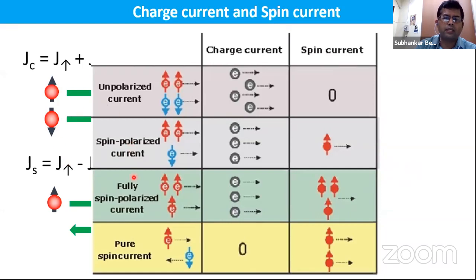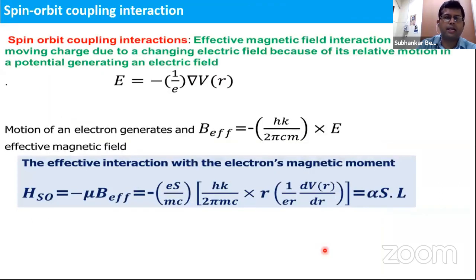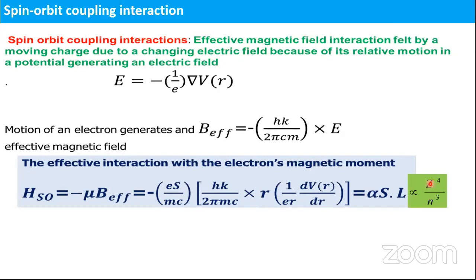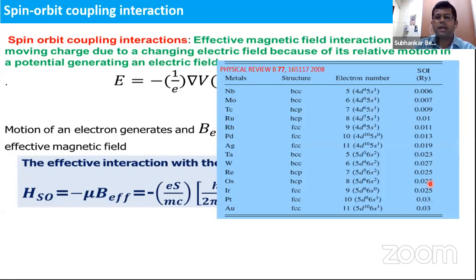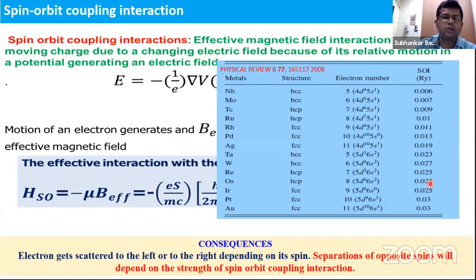What happens if you take a non-polarized current and a spin polarized current, a fully spin polarized current? In this case you have a charge current of 0. However, you can have a full spin current. That's basically the advantage. And just quickly, the idea is that for all elements, the spin orbit coupling varies with Z to the power 4. That's the reason why heavy metals have a high spin orbit coupling, but the problems are usually that they're quite expensive and there are not too many options, unfortunately, in the periodic table. So you need to really search for alternatives, and I will discuss a few today during my lecture. People have calculated the spin orbit interaction in various materials.